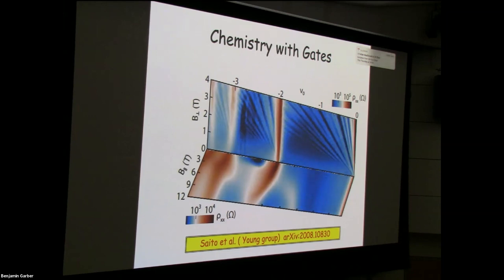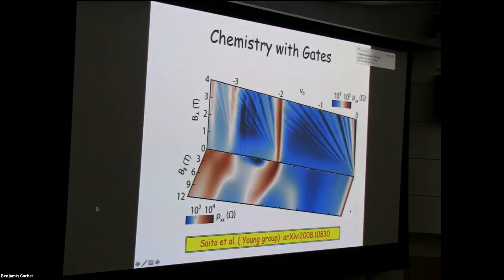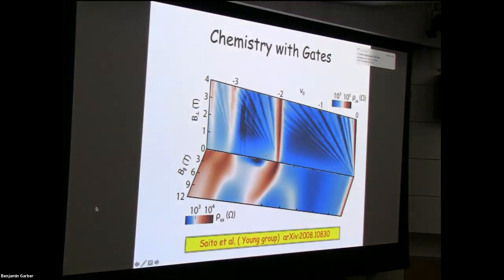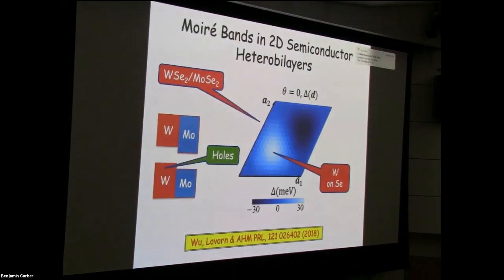So what you actually see here is data from the group of Andrea Young. It's color scale resistance versus magnetic field. It shows some important properties. For example, experts can read off of this that over much of the range of filling factor, these systems of electrons in these crystals actually behave like a Fermi liquid, which is of course common in metals. Also, behavior changes with filling factor. For example, this blue shaded region with small resistance is actually clearly established as superconductivity by now.